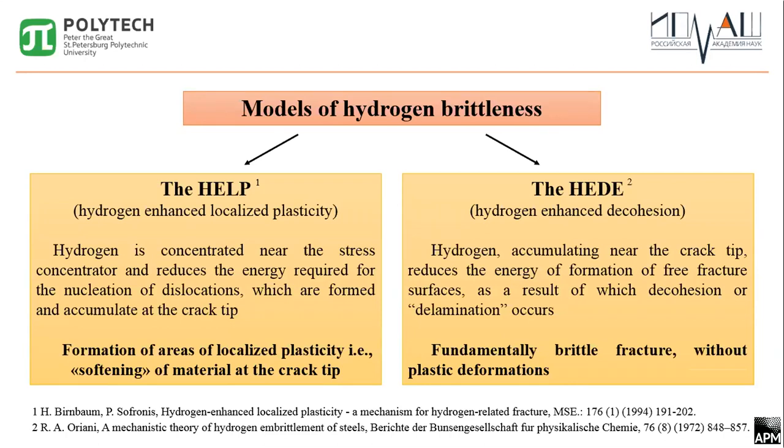Moreover, in all these works, the researchers assumed a uniform distribution of hydrogen concentration inside the metal resulting after the charging process. All changes in the hydrogen concentration were associated with its redistribution under an external load or during the crack growth. Furthermore, in all existing works, as a rule, the value of the initial hydrogen concentration is established based on the results of fitting the model parameters for comparison with the experimental data. And its value in different works varies from 5-10,000 ppm to 2 ppm.